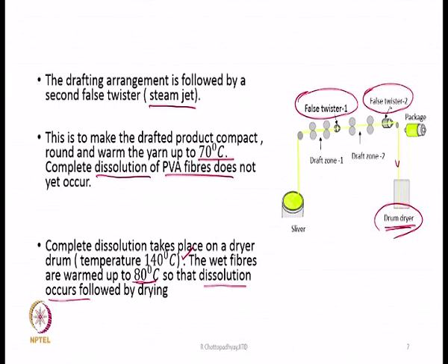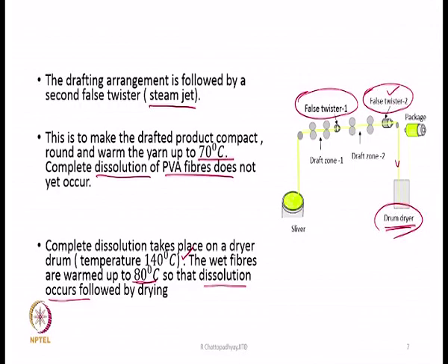So, here partial dissolution occurs when it is passing through the first twister. Temperature can go to the extent of 70 degrees centigrade. After that, it goes to the dryer, where the temperature of the dryer is 140 degrees centigrade, but depending upon the residence time, the temperature of this yarn can go up to 80 degrees centigrade, so that all the PVA fibers are completely dissolved.